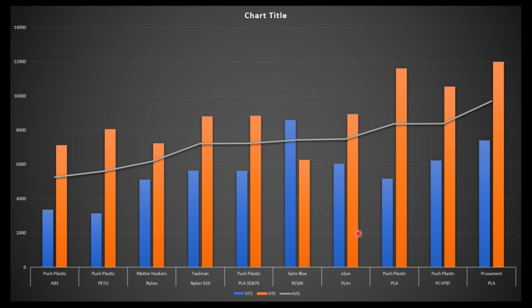And I have sorted these materials by that average, and I've done that because some filaments are a lot stronger in vertical and weaker in horizontal, or vice versa, and I thought this was a good way of sorting them. So you can see that the blue resin test sample and the eSun PLA Plus kind of fall right here near the middle, and they're once again very, very comparable. The eSun came out a tiny bit on top on the average, but I think if you tweaked how you printed the resin print, you could get that quite a bit higher. So strength-wise, the resin print's actually doing pretty good.